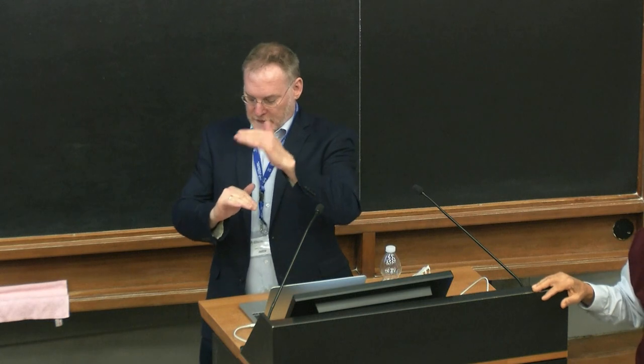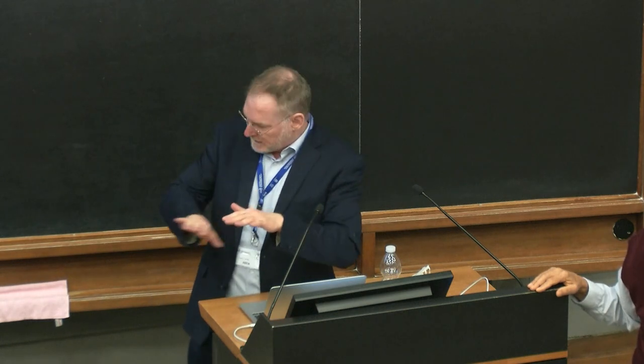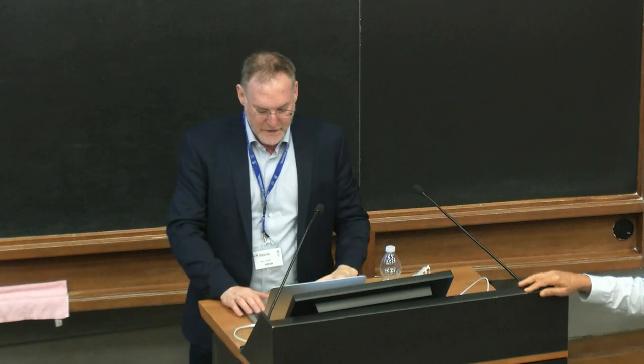But from a friction standpoint, we've seen that friction starts going up as the number of layers goes down. So with about 4 layers of graphene, it's indistinguishable from the bulk. With 3, 2, 1, the friction goes up. And that is an ongoing issue.